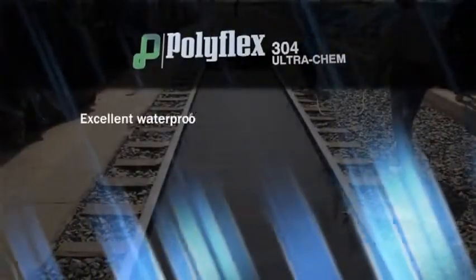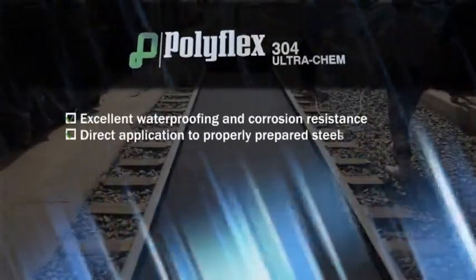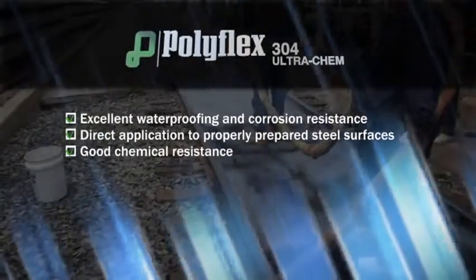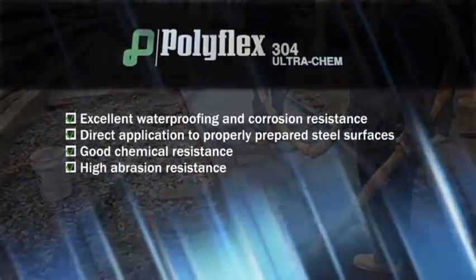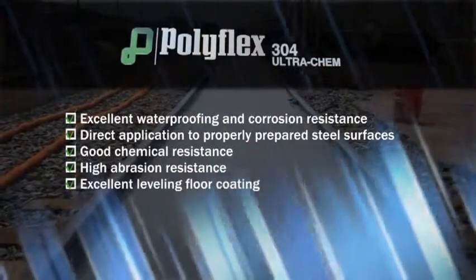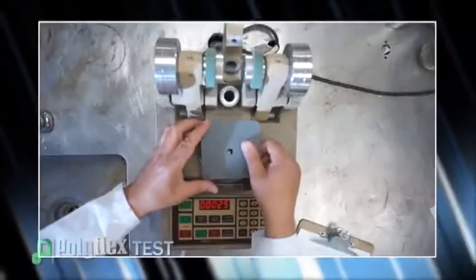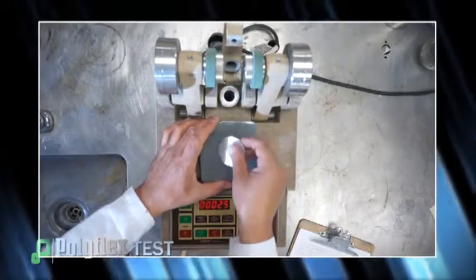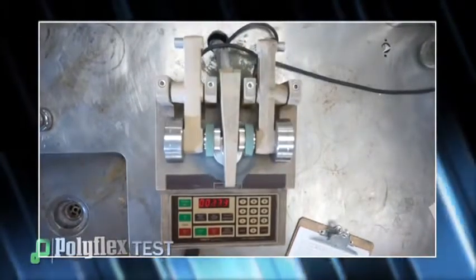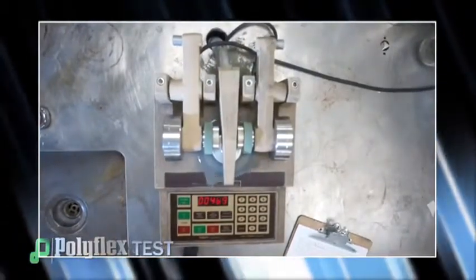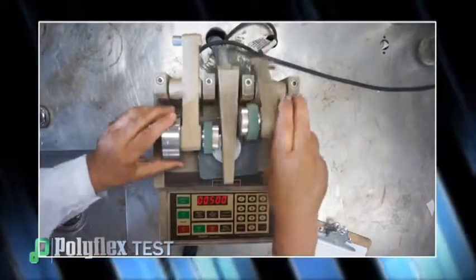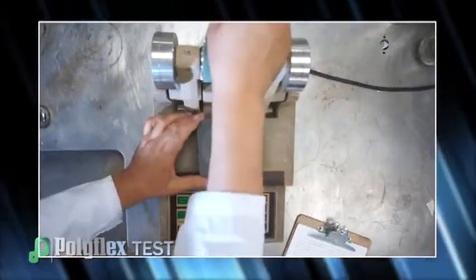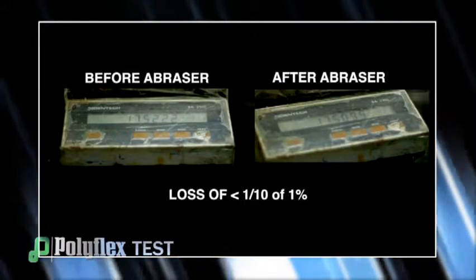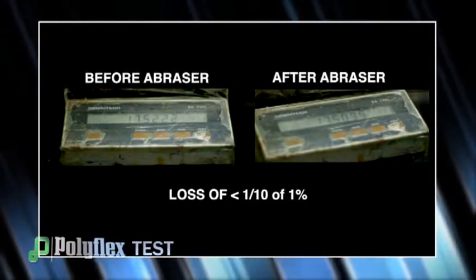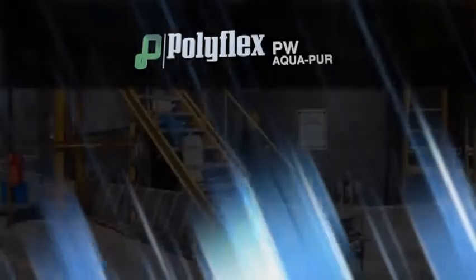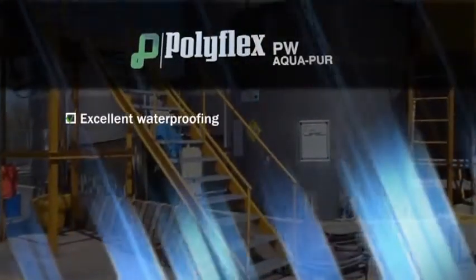Polyflex 304 Ultra Chem. Here, the Polyflex coating is run through the abrasor machine. A precision scale reads the weight before and after the abrasion to determine any loss. The results show that after 500 revolutions of the abrasor, there is a negligible loss of less than 0.1%. Polyflex PW Aqua Pure.